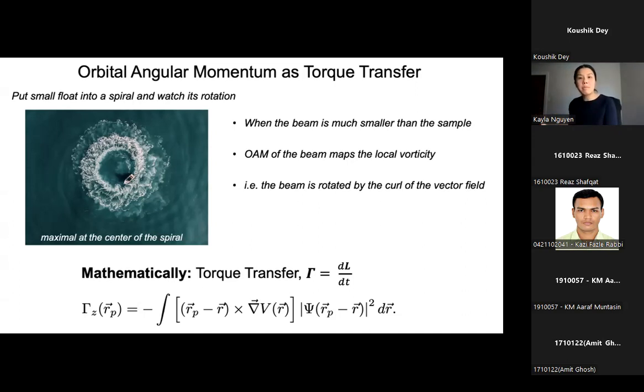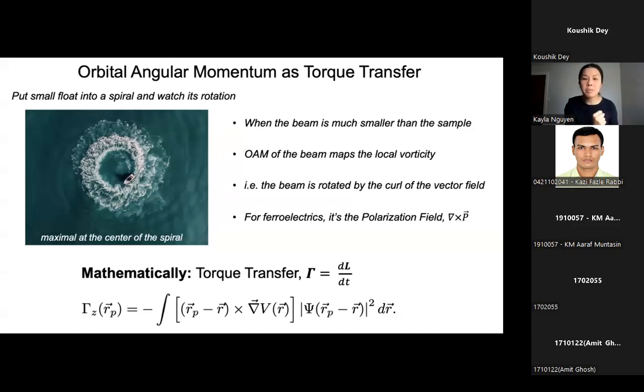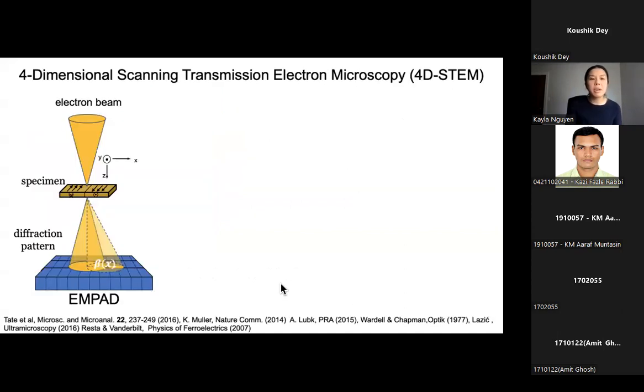When we have an electron beam that is smaller than the sample, orbital momentum can map the vorticity, i.e. the beam is rotated by the curl of the vector field. For ferroelectrics, it's the polarization field, which is del cross P. So if we want to reconstruct polarization and orbital momentum from our sample, we need to figure out how the electron beam curls around this polarization vortex. It's simply by knowing our polarization field and applying this torque transfer equation. All right, so we're going to utilize our 4-dimensional scanning transmission electron microscopy technique, or 4D STEM, to do this experiment.